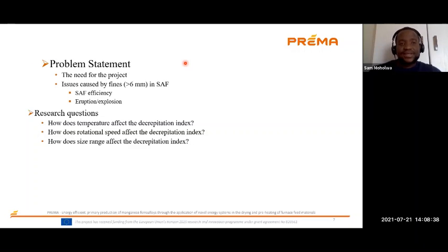Feeding fines in a SAF has a number of problems. One of them is the efficiency of the SAF. As you know, when the ore, the fluxes and the coke smelt at the bottom of these furnaces, there'll be some reaction. These reactions will produce some gases, maybe carbon dioxide and carbon monoxide. Carbon monoxide, when it moves through the burden of the material, as the gas escapes in the furnace, may produce some pre-reduction of this ore, leading us to utilizing less coke in this process.